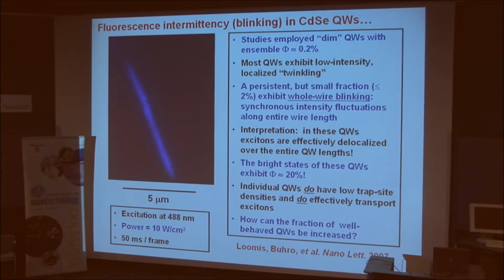But what's surprising is the pattern of this blinking behavior in this wire. Because as you may have noticed, the intensity fluctuations were completely synchronized all the way along the entire length of the wire. And if you have a wire with a highly defective surface, you do not expect to see that kind of behavior, because no exciton that's generated in one spot could survive long enough to be transported to some other area of the wire. That is to say, the blinking phenomenon should be localized. And if you see fluctuations, they should be in an uncoordinated, localized twinkling manner, like a string of uncoordinated Christmas lights.